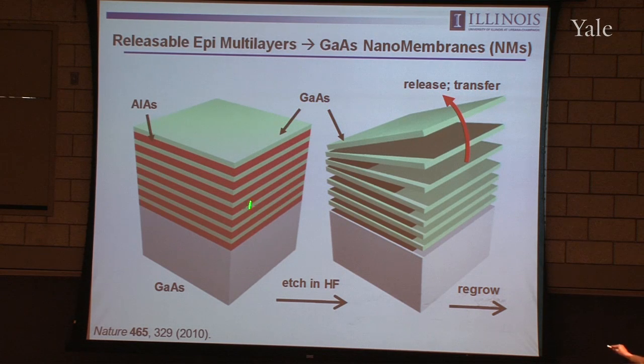Now, if you do that kind of growth strategy in a way that alternates between aluminum arsenide and gallium arsenide, you can create a multi-layer stack of this kind of material, which is the semiconductor material you want to use in your devices, separated by this other material, aluminum arsenide in this case, which isolates those sheets of gallium arsenide from one another.